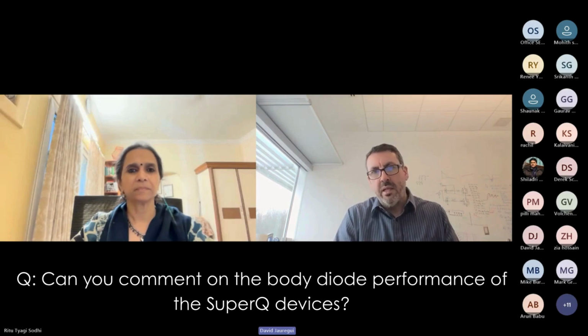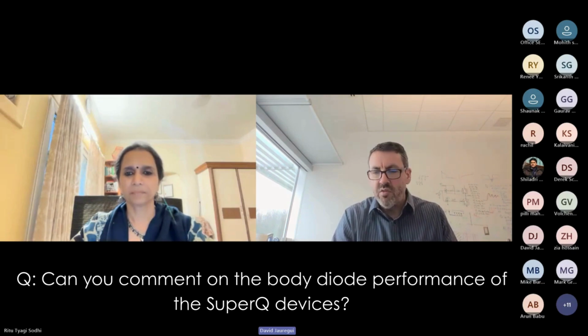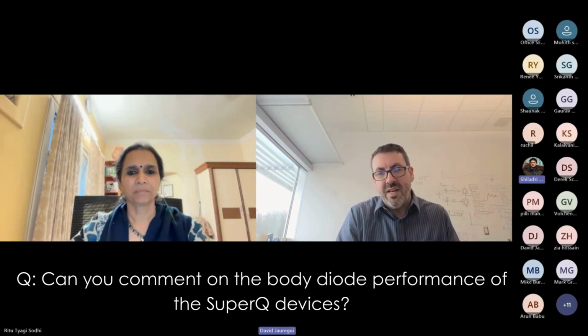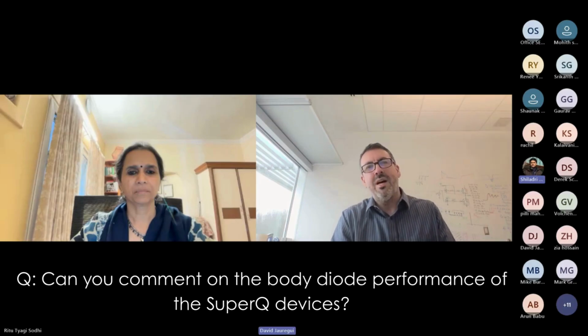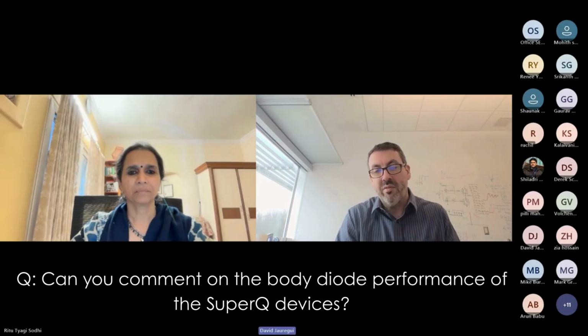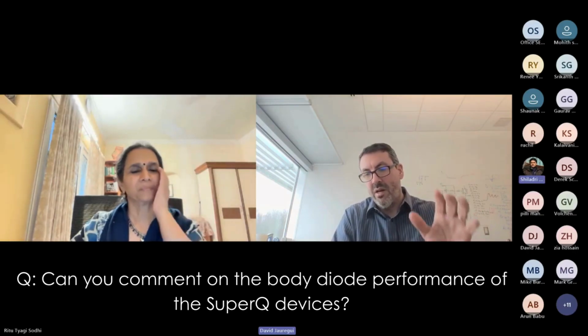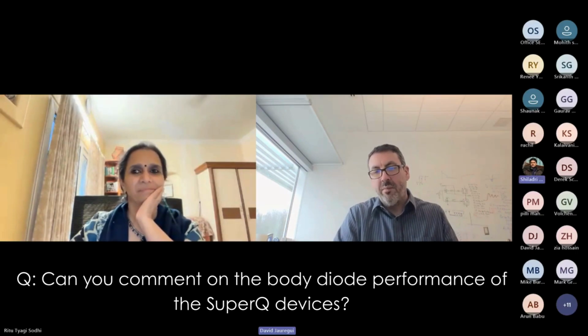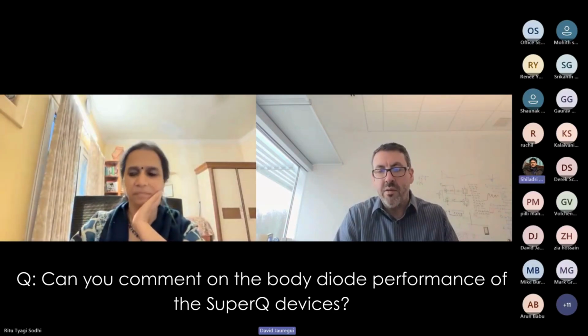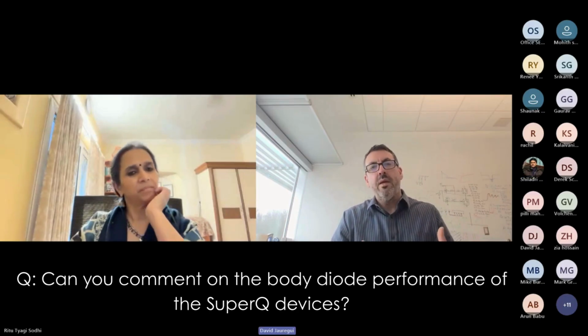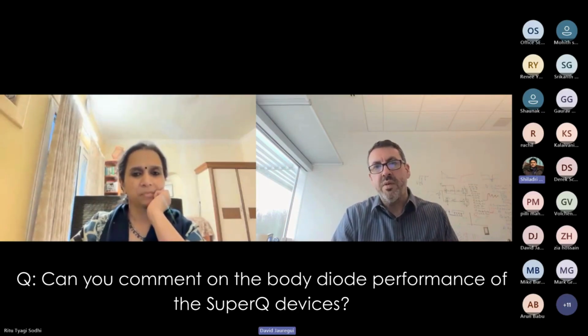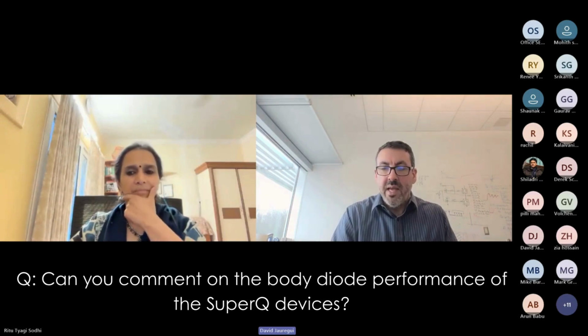But I took a step back and I looked at the platform, and I looked at what the industry is doing. For these higher voltage devices, dead times are at 100 nanoseconds or less. And as you get to 50 nanoseconds and 30 nanoseconds, the impact of reverse recovery becomes a lot less for these higher voltage devices. And like I said, I've got an IEEE paper that is in the process of being peer reviewed and accepted, and I'll gladly send it to you guys for reading. My point is that the impact of reverse recovery is becoming less because of the narrower dead times, and not because of what we drew.